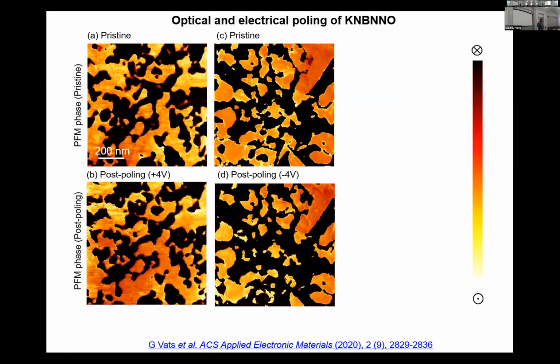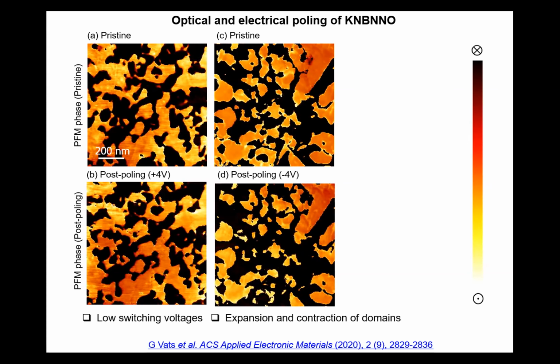The interesting point is, I mentioned that this was a 100 micron thick polycrystalline ceramic sample, and I'm applying very low voltages, +4 volts. And this kind of measurement can be done even with lower; I tried up to 0.5 volts. If you imagine the electric field I'm applying, it's not that high. And with that field, I'm able to move the ferroelectric domains, which is interesting because now we have low voltage switching or low voltage movement of ferroelectric domains.